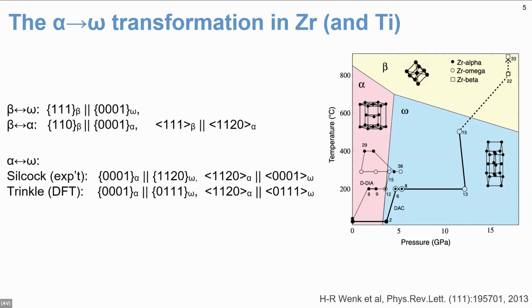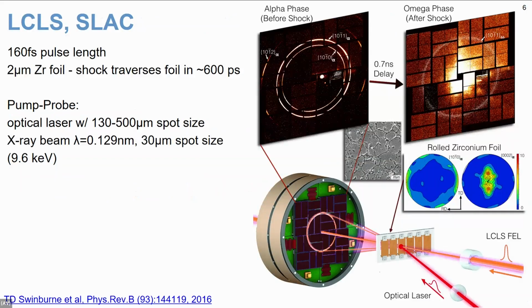Now, the pathway to go between these different structures we usually measure by static experiments, or we can model by DFT. But the question then is, well, if you go fast, is it the same? And it turns out that it may not be. So this is the sort of thing we're doing. We're hitting a foil in this case with an optical probe. It has to be a foil because the beam is so low energy. And then we rattle a shockwave through it and see the new phase appearing.